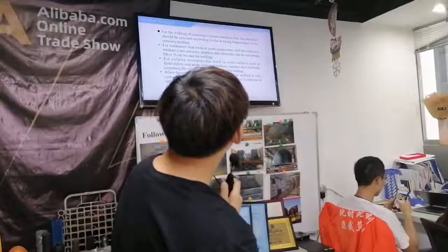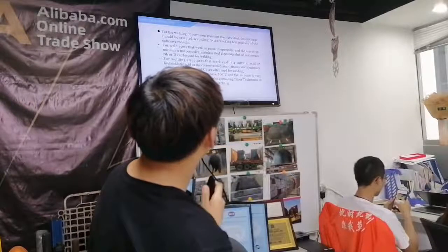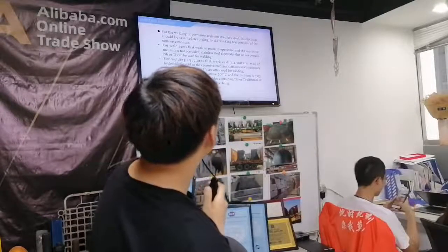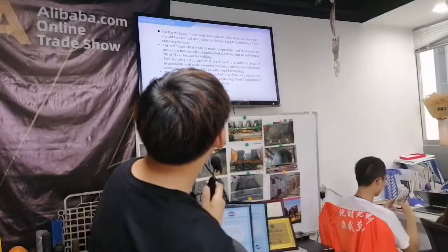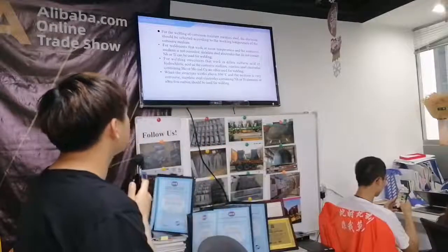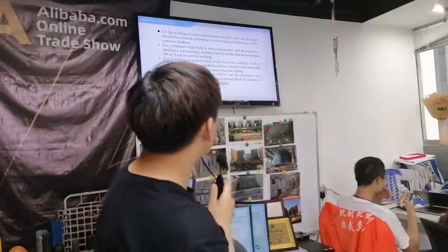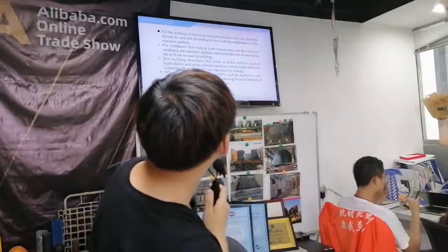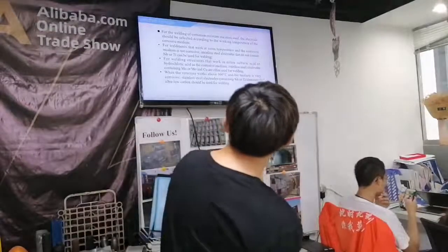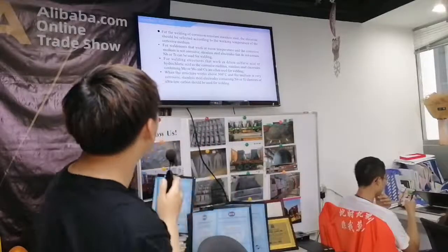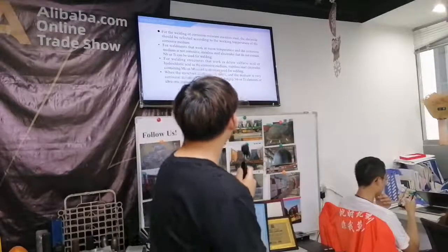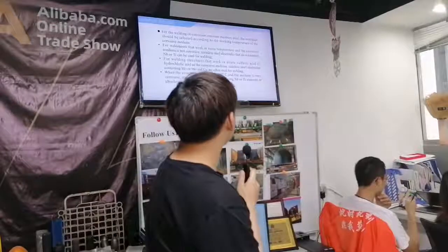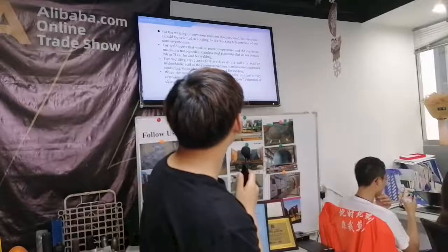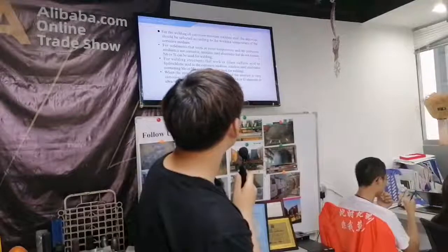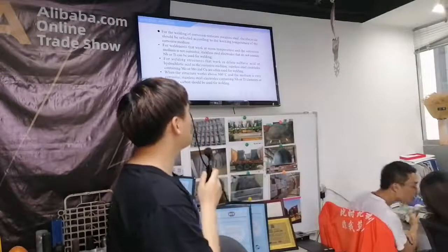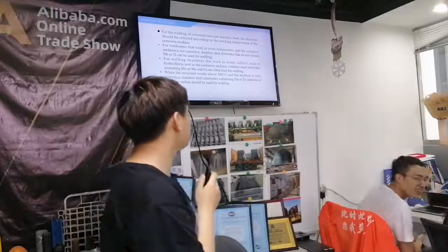For welding structures that work in dilute sulfuric acid or hydrochloric acid as the corrosive medium, stainless steel electrodes containing Mo or copper are often used for welding. When the structure works above 300 degrees and the medium is very corrosive, stainless steel electrodes containing Nb or Ti elements or ultra-low carbon should be used for welding.